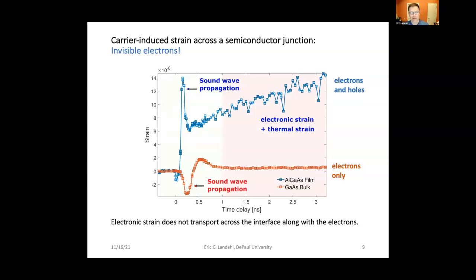This is an actual plot of the strain taken from those peak shifts. We see at early times, within a nanosecond, sound wave propagation. It's been well studied. But then we see electronic and thermal strain. As mentioned, hard to tell them apart when you are only measuring the strain effects, but presumably resulting from both electrons and holes being present in the film, the AlGaAs layer. However, in the bulk, there is no modulation really whatsoever once that impulsive strain wave passes. And so we conclude from this, electronic strain does not transport across the interface along with the electrons. That's a rather strong claim.